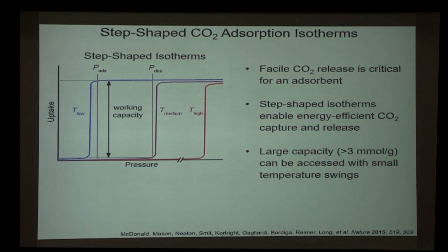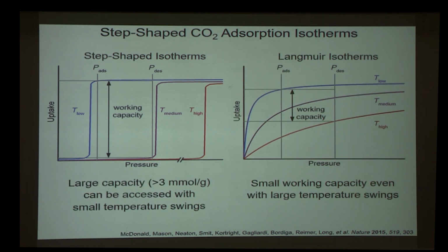So when you have a step-shaped isotherm, it is tremendously advantageous for the capture and efficient release. It is because a massive working capacity can be accessed with only a moderate temperature swing. This is directly related to the ability of these materials to abruptly transition from completely full of CO2 to completely empty. In contrast, traditional adsorbents have a Langmuir isotherm shape, such as these depicted here. And what happens is at very high temperatures, corresponding to this red curve, you still have some CO2 captured in the material. So even with large temperature swings, you can access only a modest working capacity.